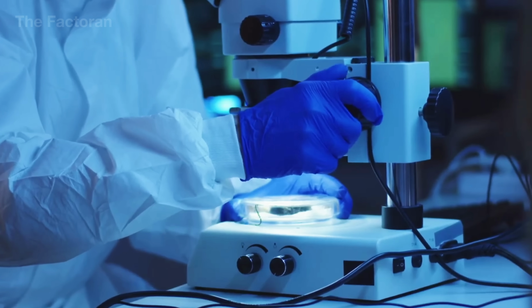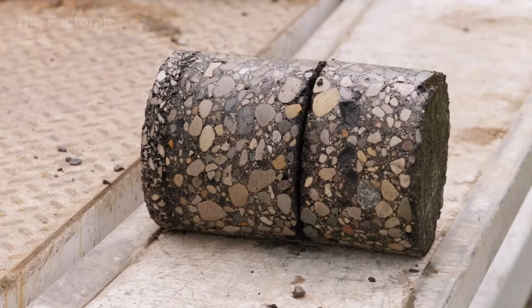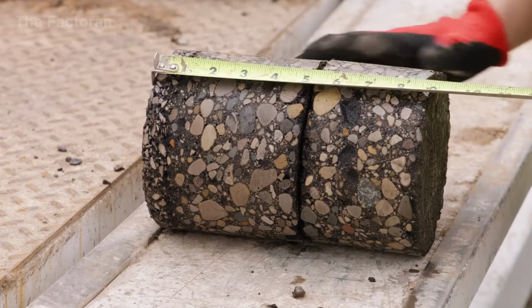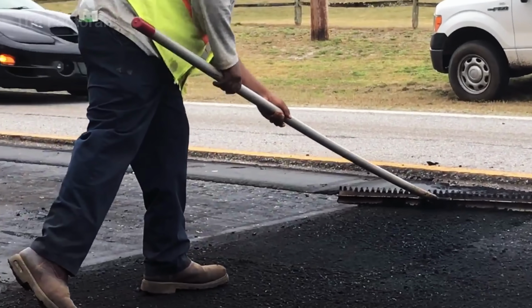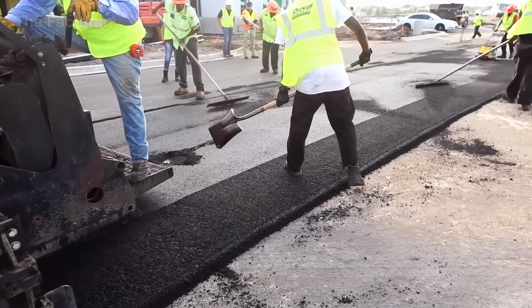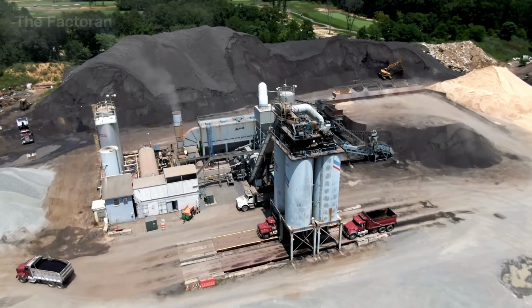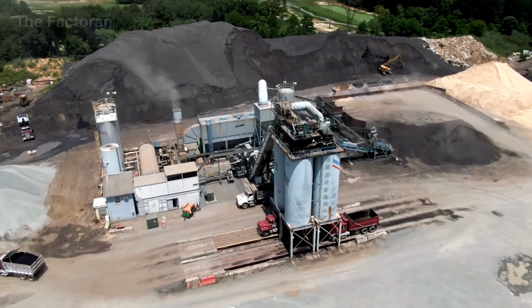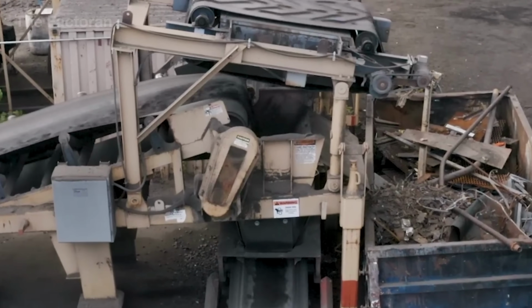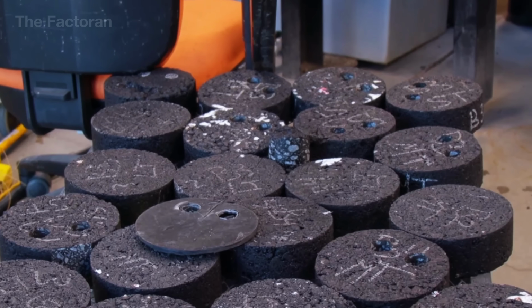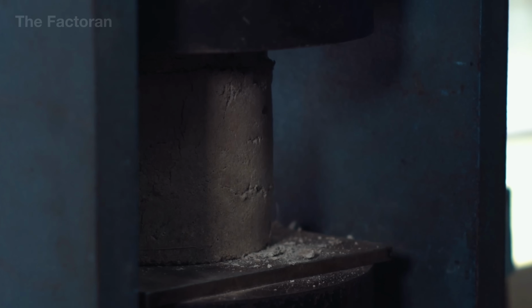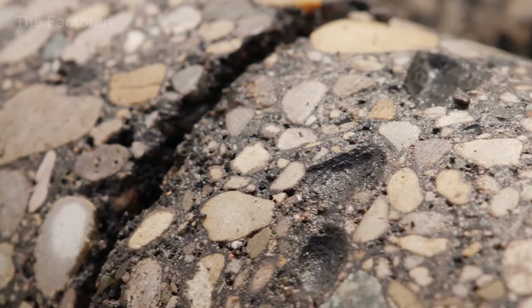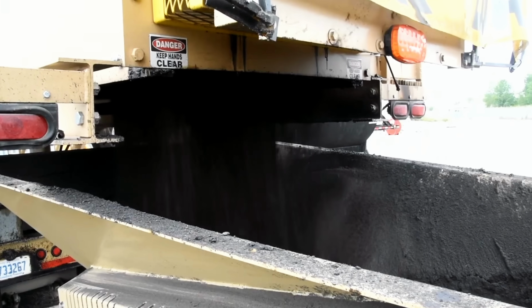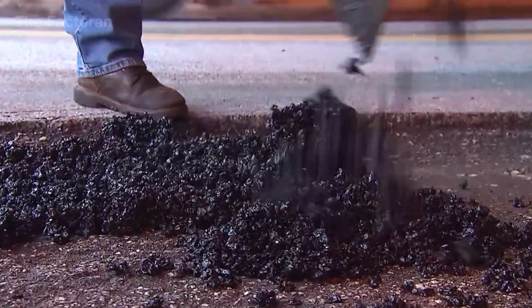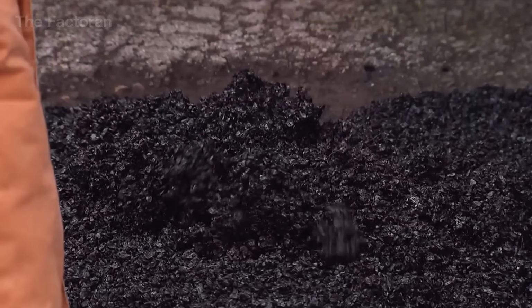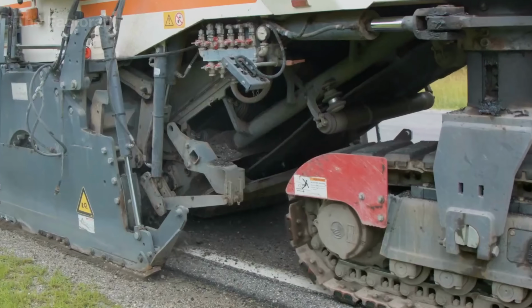Beyond plant recycling, many regions also adopt in-place recycling. In this method, specialized machines mill the old surface while spraying rejuvenating liquid binder directly onto the road, which is then compacted immediately on site. This approach saves transport costs and reduces road closure times. The result is clear. Instead of becoming waste, nearly every ton of worn pavement is returned to serve new roads. Some modern facilities now achieve 100% recycled content, making asphalt one of the longest-lived construction materials.